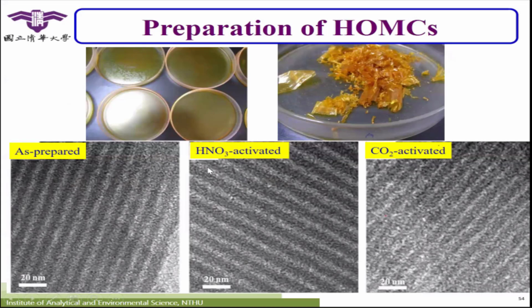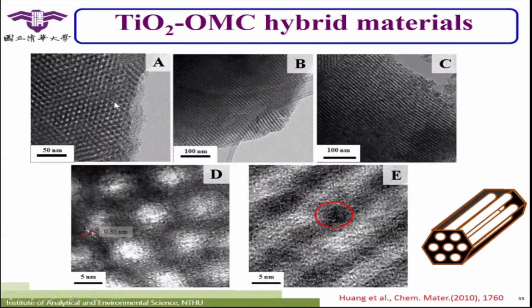Okay, this one is their pore. When you enlarge it using high-resolution TEM, we can see their structure. From the high-resolution TEM we can see the pores here, and the arrangement of the pores is quite homogeneous. So we call this one highly ordered.